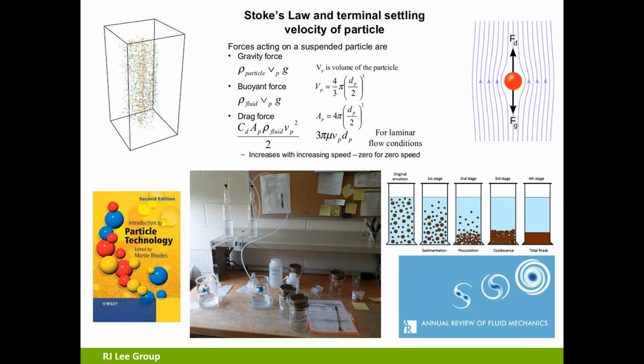Now we're going to take this material, and this was done a few years ago before we introduced the VFF process, which I'll discuss in a second. This used Stokes settling. Stokes settling is an older process. It's been around a long time. It's based on density and liquid particle technology, as well as fluid mechanics and particle settling. And it's got derivations and equations that you use for the settling time in order to separate the less than 10 micron or less than 5 or whatever size fraction you want from the balance of the particulate. It has some weaknesses, which we've overcome with the VFF.